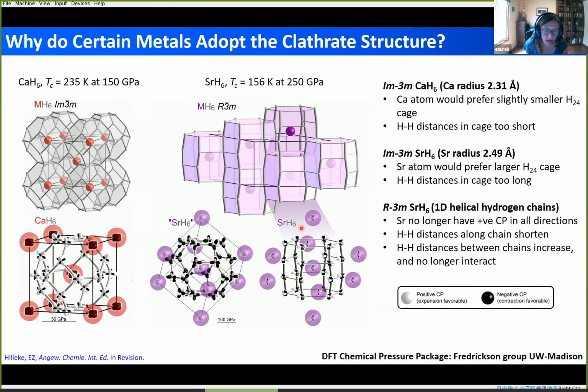Now taking a look at the dimer structure, where you've undergone this structural transition to form 1D chains, we see there is no longer any chemical pressure along the hydrogen-hydrogen contacts where there is no bonding. The chemical pressure along this hydrogen-hydrogen chain has been relieved. Within strontium itself, there are no chemical pressures of large magnitude—just little bits of CP along this C-axis. So we've relieved the chemical pressure by undergoing this structural distortion.